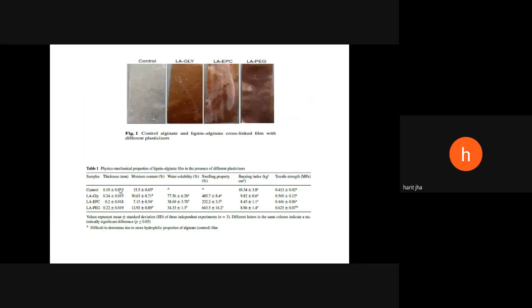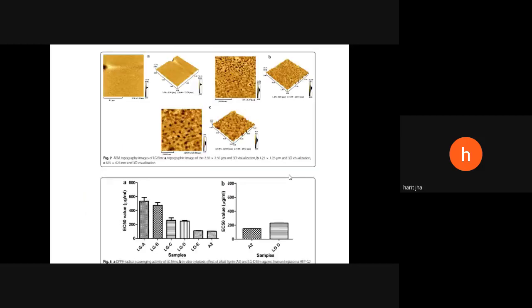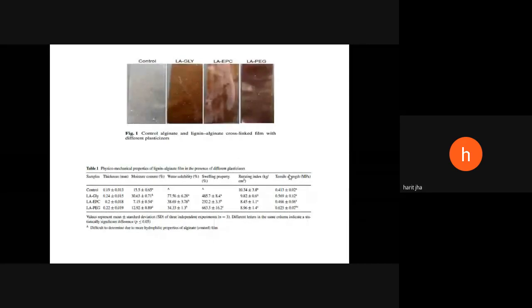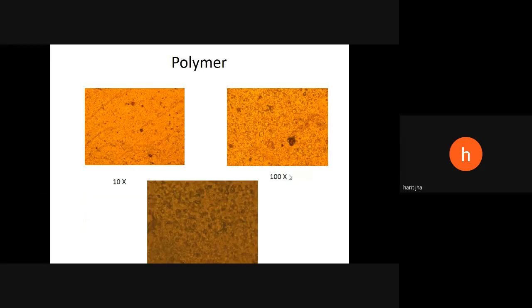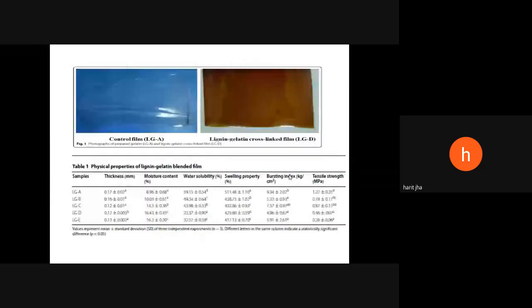We have seen the physicochemical properties like thickness, moisture, water solubility, swelling property, bursting index, and tensile strength. One of the reasons for assessing these properties was that when you use a material for packaging, the important thing is that beside the tensile strength and burst index, that is strength property, they should be able to pick up heavy load. Beside that, they should also not absorb a lot of water, and they should not be water soluble. The swelling property should be minimized. The bursting index should be high. The tensile strength should be good. And then only that particular polymer can survive as a packaging material. So we don't want it to absorb water and get solubilized when you're using it as a packaging material.